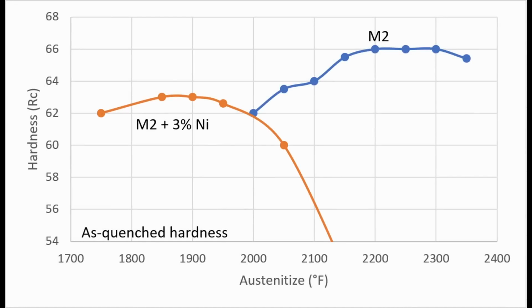Another issue with nickel is that it reduces the temperature where martensite forms. Martensite is the hard phase that we form during quenching. So we quench the steel in oil, it gets very hard, and that's what gives us our nice strength and edge retention properties in the steel. And when martensite formation occurs too low, you have retained austenite. So the austenite was the high temperature phase. If it did not transform to martensite, it is retained, and that soft austenite does not contribute to our hardness and strength and edge retention.